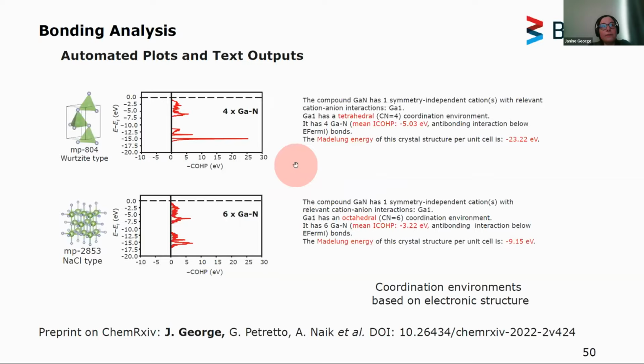And as I said, we then get automated plots and text outputs. It will really find out which are the most important bonds in the crystal structure. It will analyze the so-called integrated COHPs, ICOHP, which basically describe the bond strengths. Based on this, it will also be able to determine a coordination environment. So we take the positions based on the ICOHP values from the LOBSTER output, put it back into ChemEnv to find out which kind of coordination environment we have. So we again use these continuous symmetry measures that I talked about in the first part of the talk. And then we really also get coordination environments based on the electronic structure.